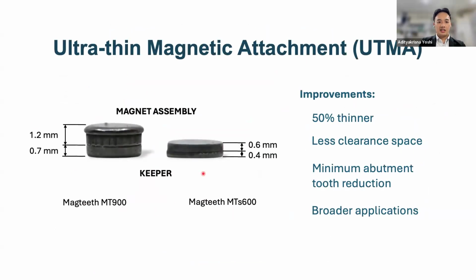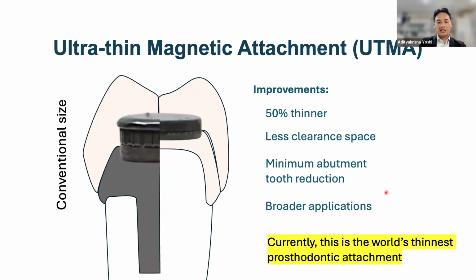These are the dimensional comparisons between the ultra-thin type and the conventional type of magnetic attachment using the same brand. And other brands usually also start from this dimension, which in total requires around 2 millimeters or above with similar diameter. The presence of UTMA makes it 50% thinner and requires less clearance space, minimizing abutment tooth reduction and also prosthesis space. And this is currently the world's thinnest prosthodontic attachment available.